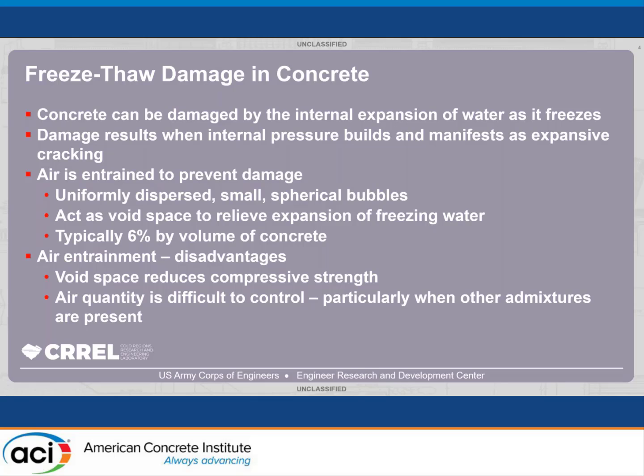And so your typical concrete mixture is going to be about 6% by volume air entrainment. But in colder regions where you're expecting a lot more freezing and thawing, you might have a little bit more than 6%. And in southern regions where you don't expect as much freezing and thawing, it could be even lower. So air entrainment is very useful, but there are some disadvantages. With that void space, the more space you have of voids, the lower your compressive strength is going to be. So you really want to find a good balance.